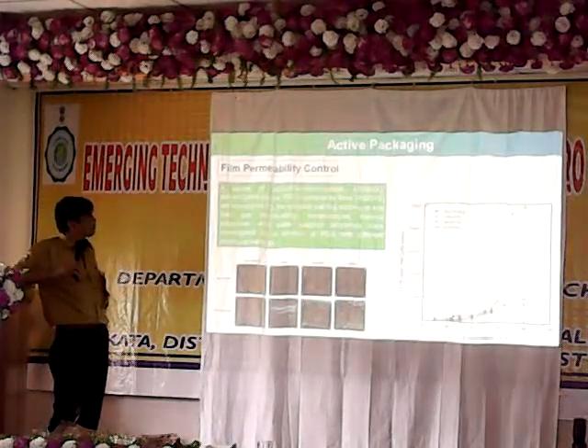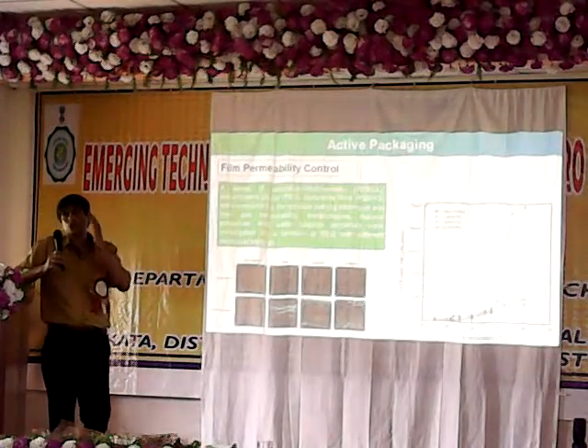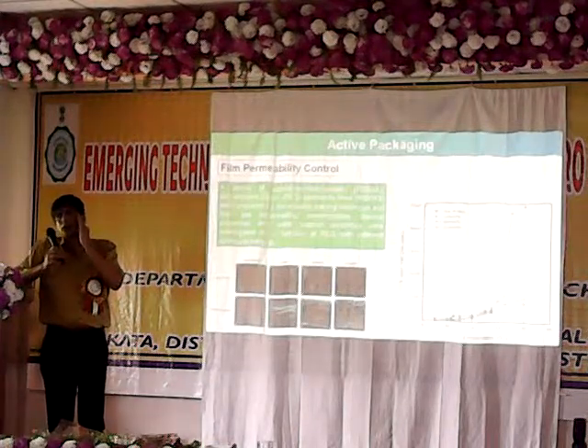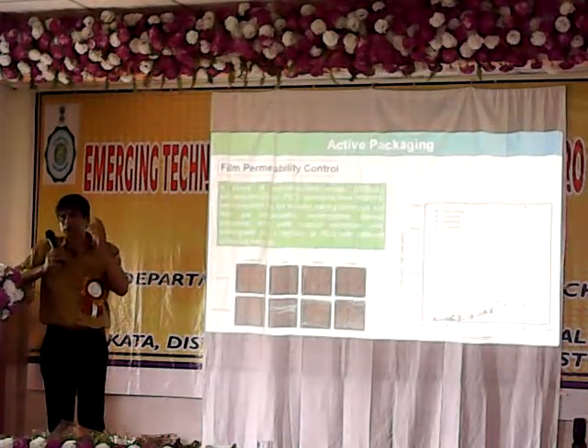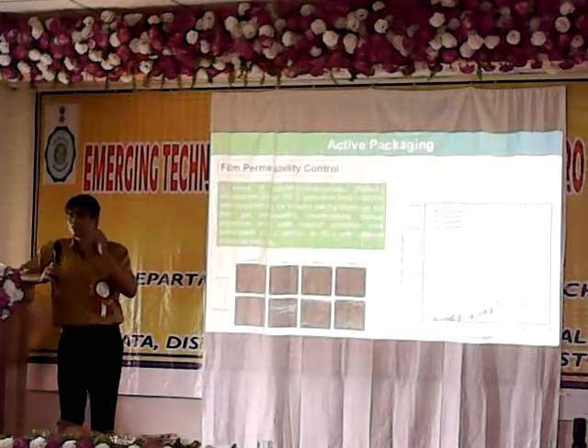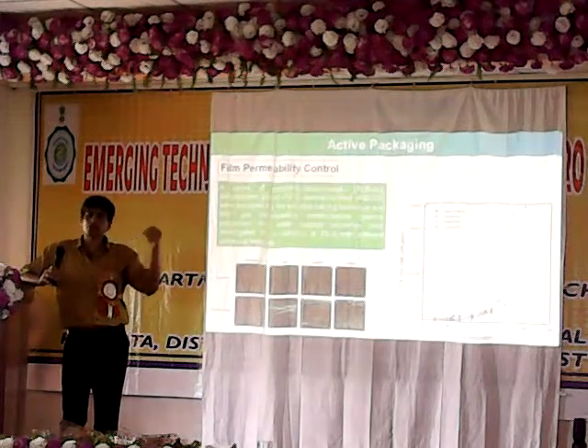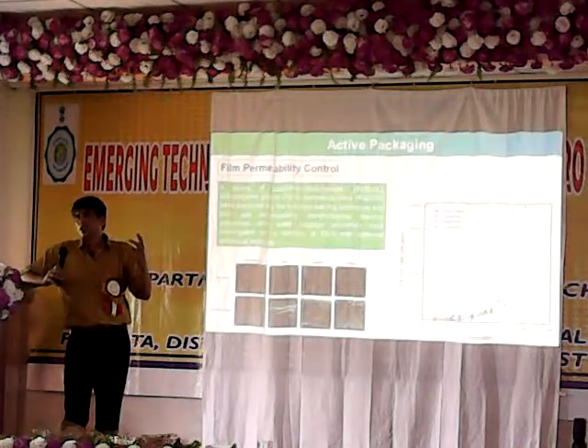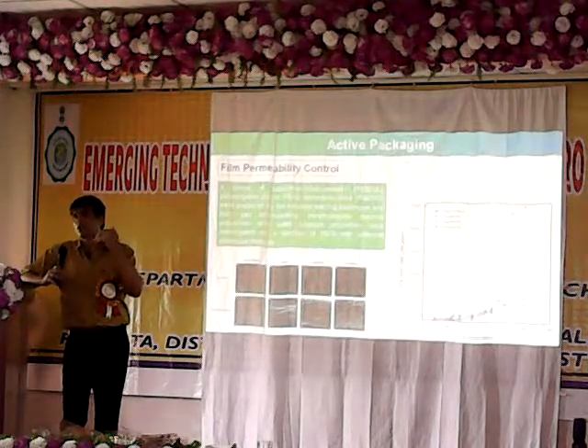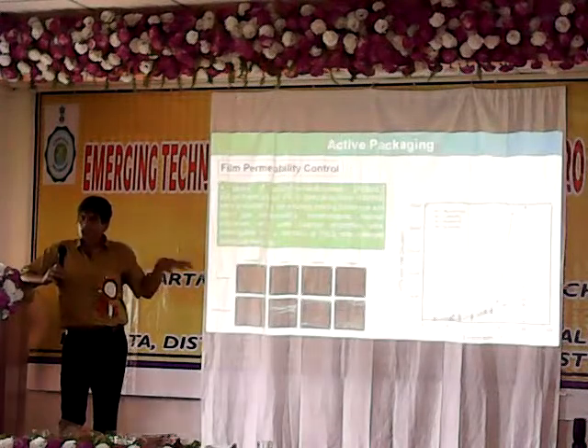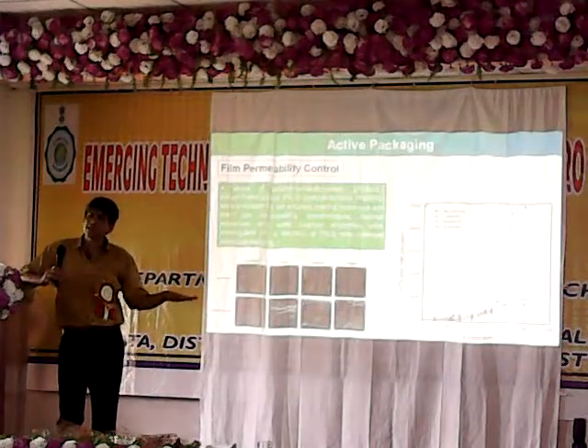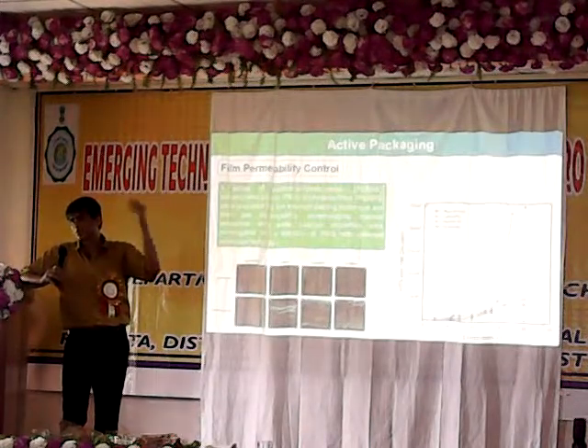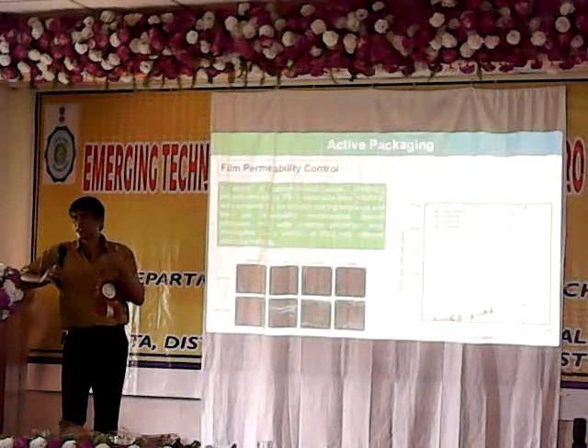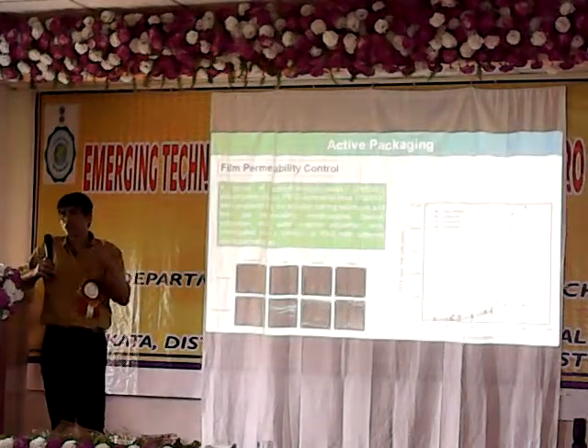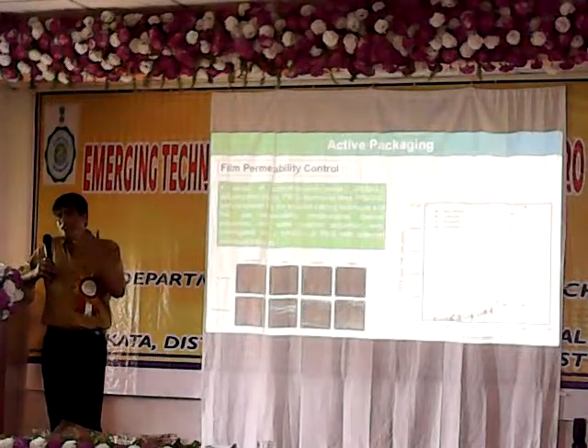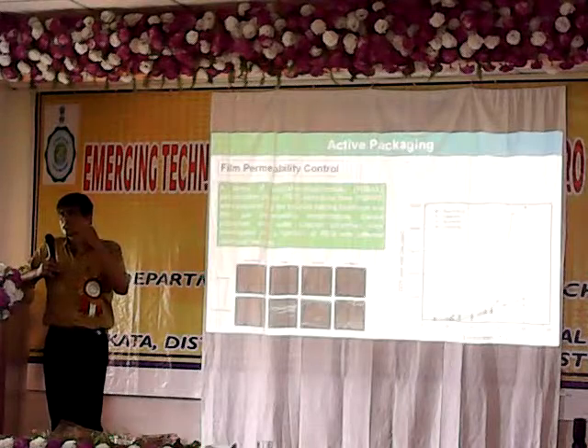What is film permeability control? Now we have seen that we are using a lot of polymers, right? These polymers have their permeability depending upon temperature, but there is very little variation in the permeability of the film to a particular gas, be it carbon dioxide or oxygen. In a situation like India where refrigerated transport is not available, during distribution the temperature may go from 10 degrees to 40 or even 50 degrees centigrade. Now, the respiration rate at 10 degrees is lower, if I design the package for a product at that temperature.